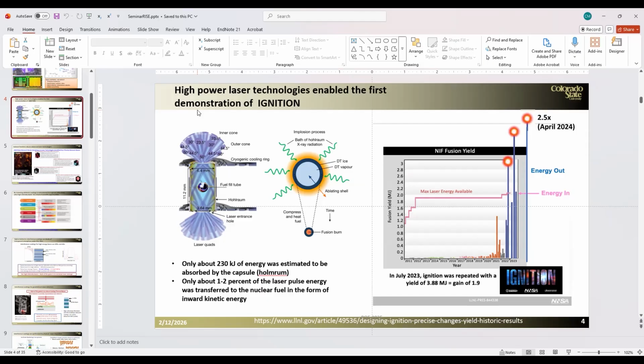to repair the optics. The optics at NIF, just to give you an idea, are approximately 70 centimeters by 40 or 50 centimeters. They're huge. And their beams are huge, because they have to keep the fluence down. As a result of that, if they see an incipient damage on any of the optics, they can repair that. And they have a way to do it.